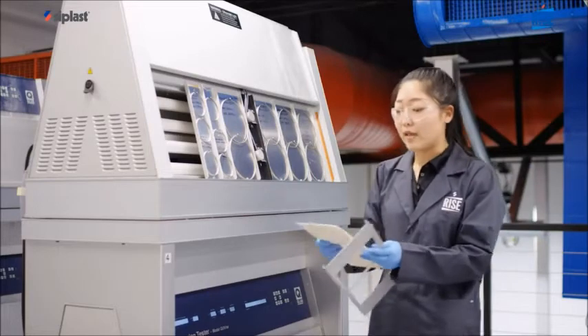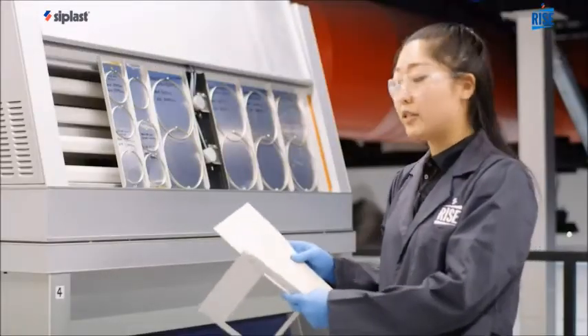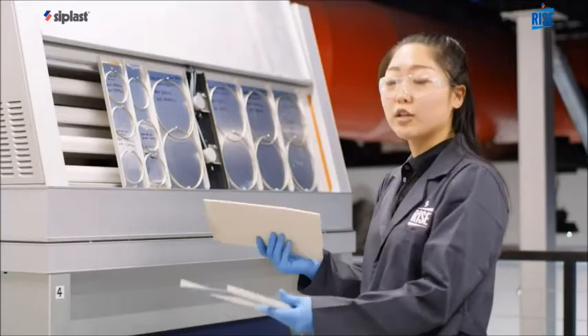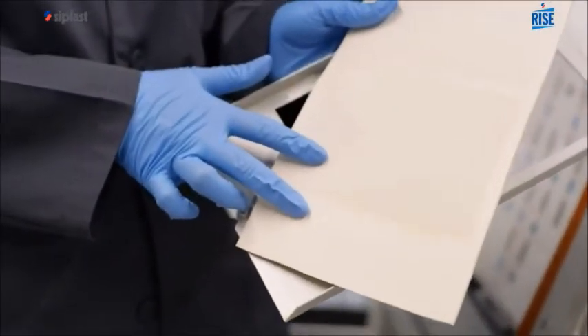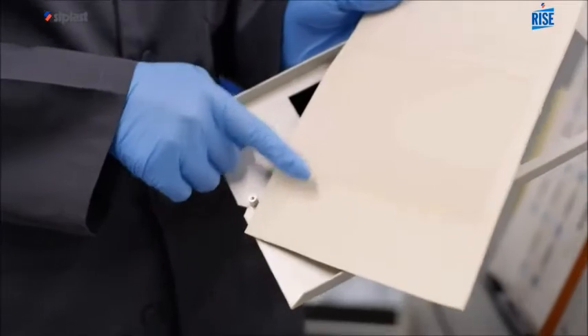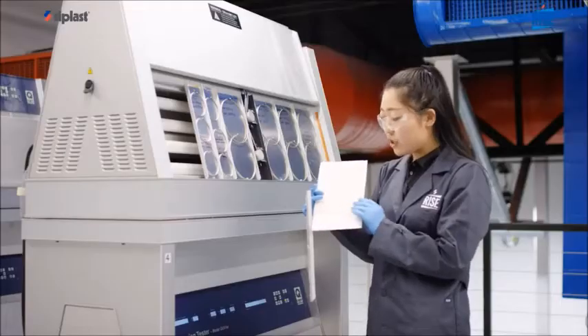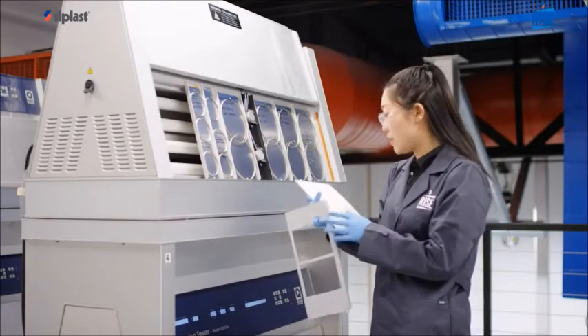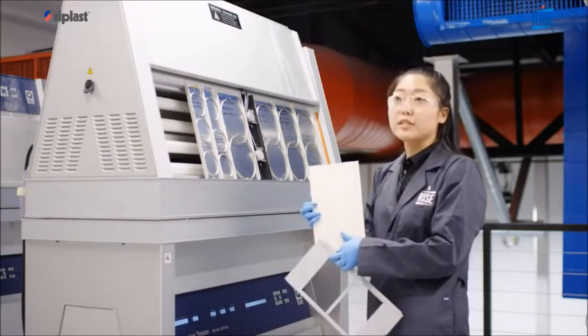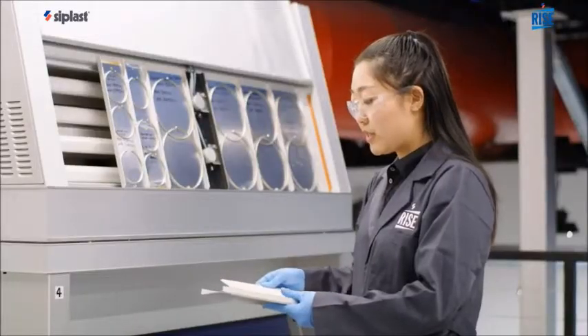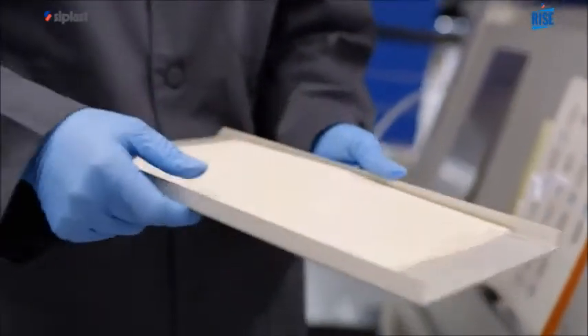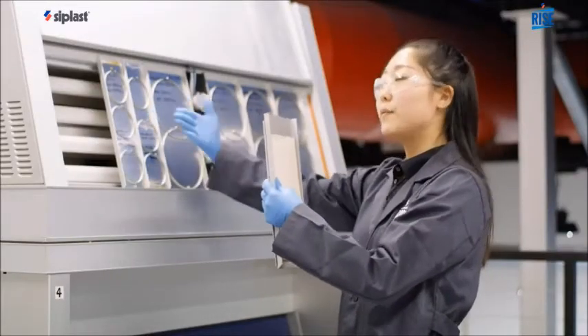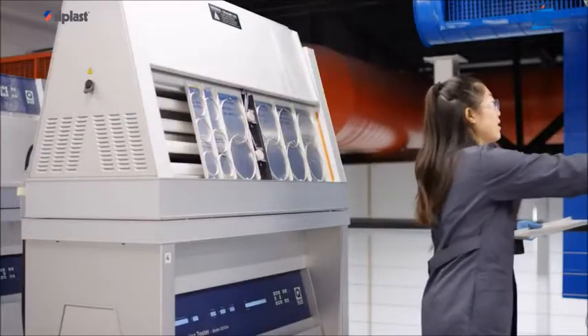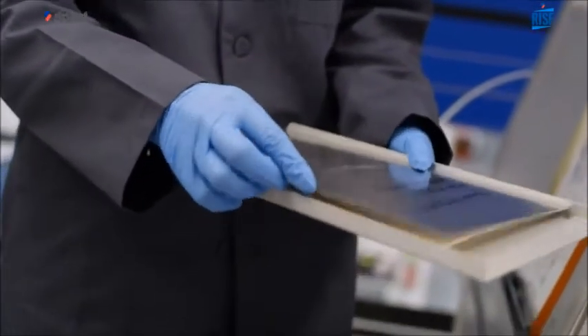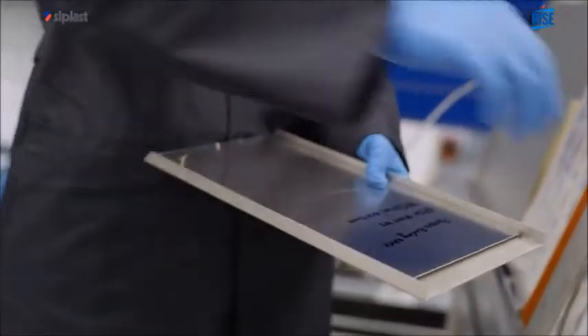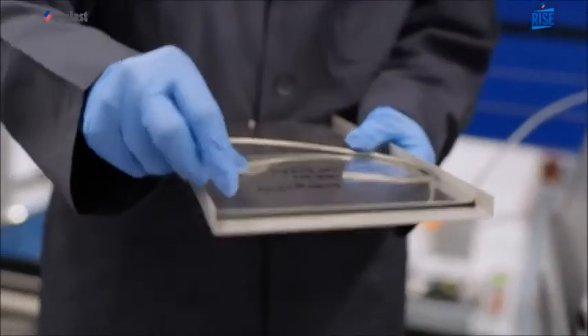We already have this sample out here that's been aged for about 2,000 hours, but we're gonna put it back to run additional testing. You can tell from the 2,000 hours how the samples changed, the colors got a little chalky or yellow, just from the visual representation. So I'm just going to put it back down, and we always want to have it face downward because the lights are on the inside of the unit. And we would have a back holder to have it pressed down onto our panel. So we would secure it with some rings.